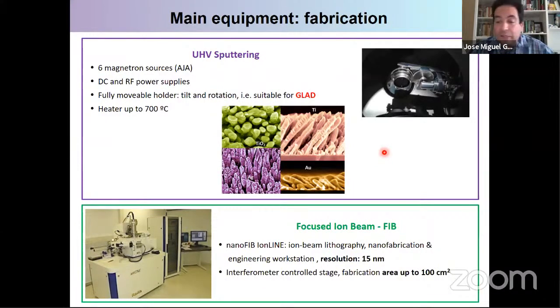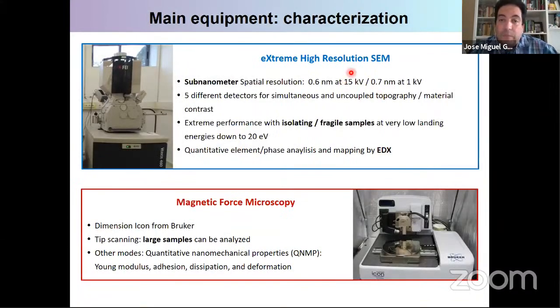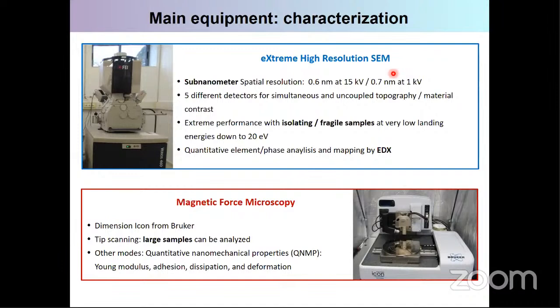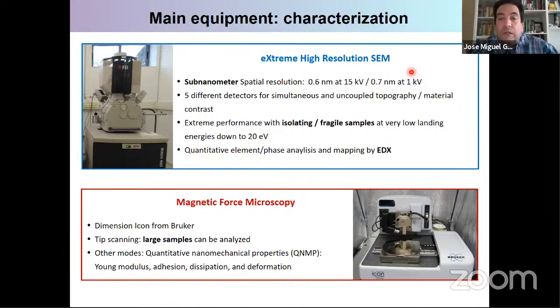And regarding characterization, we have an extreme high resolution SEM microscope that can have a resolution below 1 nanometer at 1 kilovolt. It is suitable to work with low voltages, so we can image insulating samples, for instance, biological samples, without a metallic coating on top. Which is very useful for this kind of sample. And we have a magnetic force microscope, and it is a real tip scanning microscope.